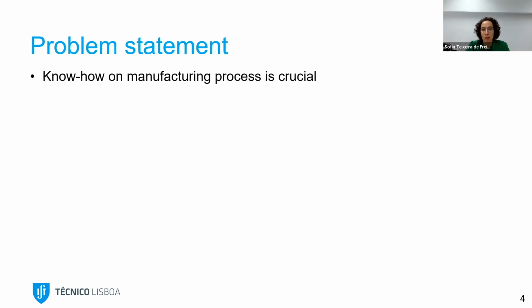However, applying bonded joints doesn't come without challenges. The first main challenge is that you need to know what you're doing when you apply a bonded joint. While with rivets and fasteners the manufacturing is easier, you just need to drill a hole and put a rivet in it, for bonded joints you need really good quality control of the manufacturing. You need to know which surface treatment to use for the substrates, and which adhesive is the best to use for the specific application. So the quality of the manufacturing is crucial for having a good joint.